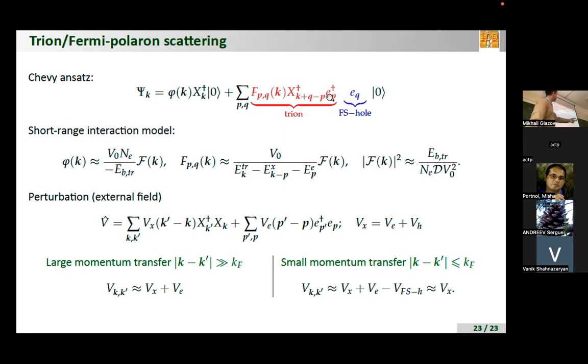You pick up an electron from below the Fermi level and you have a hole there. In fact, if you look at this three-particle correlation, exciton plus electron, its wave function is the one we described for the trion. But you have this Fermi sea hole, and this was the idea of Suris, of course. And then you can also interpret in terms of quadrons and speak about their fine structure. But basically, if you do this approach, at least in very simple conditions, you recover all the physics of Fermi polarons. And at low density, where the Fermi energy is much smaller than the trion binding energy, typically this Fermi sea hole plays no role, and you may speak about trions. You can reproduce the same results. So these are two approaches from different density regimes.